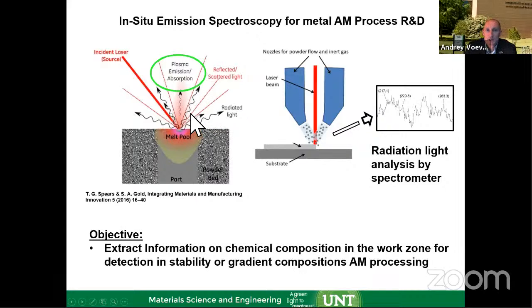And that characteristic light is very specific to the type of vapor present right on the surface of the melt pool. If you have powder of different composition, aluminum, titanium, vanadium, etc., then you can expect that the characteristic light will contain the wavelengths of those particular elements. And if you start varying these elements and their concentrations, then the light emitted should be proportional in intensity to the number of those atoms present. This is the idea: using non-destructive spectroscopy of the radiated emission caused by the working laser as basically a fingerprint, looking at the peaks, analyzing them, and seeing if we can use it for elemental composition monitoring of the melt pool.